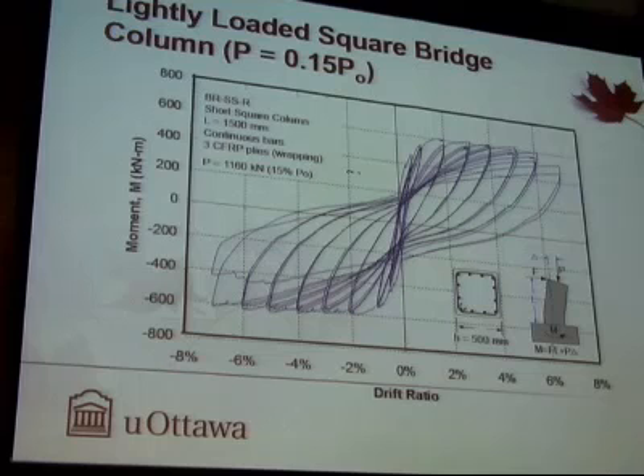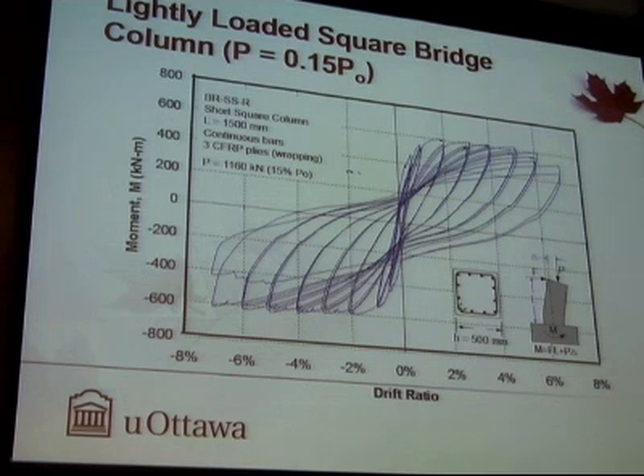So the first retrofit project that I will talk about involves use of FRPs, fiber reinforced polymers. Nowadays, of course, it's widely accepted in the construction industry to use carbon fibers and glass fibers and wrap columns for all of those three deficiencies that I talked about. The important point that I wish to make here is the importance of axial load, which distinguishes bridge columns from building columns. Typically, bridge columns are subjected to about 15% of concentric column capacity in terms of axial load. They're essentially bending elements. And in these columns, if you do provide transverse fiber wraps, then you're not really using the potential of these fibers. Columns fail through other mechanisms prior to reaching the strength of the fibers.